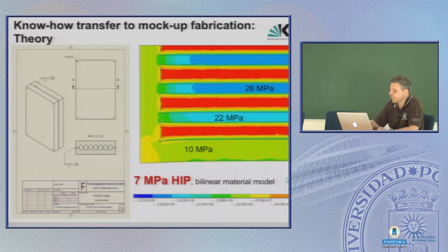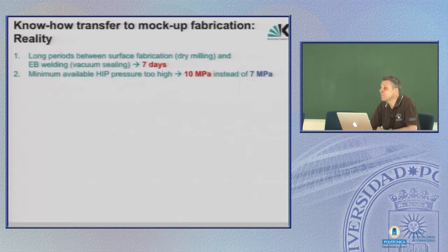So anyway, we gave this to industry to press it together, or to weld it together, and then reality came into play. The workshop forgot to dry mill the surfaces and immediately vacuum seal them, so the parts were stored for at least a week. I'm not sure how long it really was, but it was certainly a week. After that, they welded them tight, and the hot isostatic press was not able to deliver only 7 MPa. It starts at 10 MPa, and without asking us, they said, we don't mind 7 or 10 MPa, this doesn't matter, and so they fabricated this at 10 MPa. That's reality.